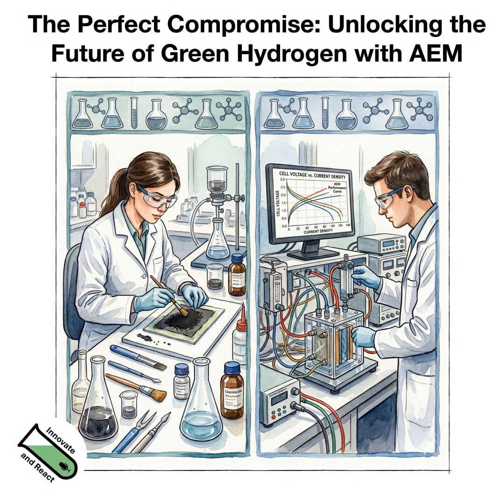I always think about it like you have your catalytic material which wants to do the reaction as a part of itself, and some materials want to do more of it and want to do it better because their edges are so aligned and they're nice materials, and then the whole complicated chemistry stuff. And the other side is how much of the material is actually part of the reaction. So in a reduced system like a rotating disc electrode, it's quite easy to find out how much catalyst is actually part of the reaction. We call it the electrochemical surface area. For most materials that's easier to find out. There are methods. For some materials, like Miriam mentioned, this nickel iron layered double hydroxide, it's not so easy because